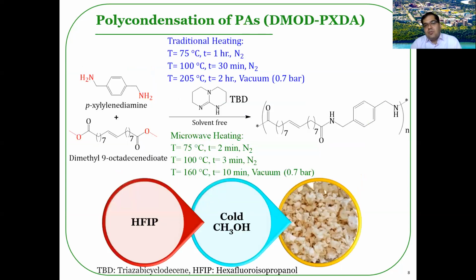The semi-aromatic polyamides, DMOD-PXDA, was produced through the reaction between dimethyl 9-octadecenedioate and an aromatic diamine called xylylene diamine through a stepwise heating process using TBD as a catalyst and in a solvent-free medium.